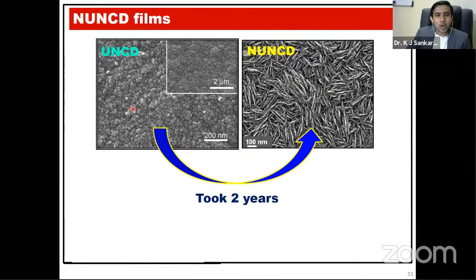By optimization of the growth conditions of UNCD from methane and argon to methane and nitrogen, I just say it easily, like methane argon to methane nitrogen. But we need to optimize the growth conditions in terms of pressure, microwave power, gas conditions like the flow rate of the gases and the methane and nitrogen composition, and also the substrate temperature and the distance between the substrate and the plasma. So many parameters have to be optimized to achieve this perfect NUNCD wire-like morphological diamond film. So it took 2 years for me to get these NUNCD films.